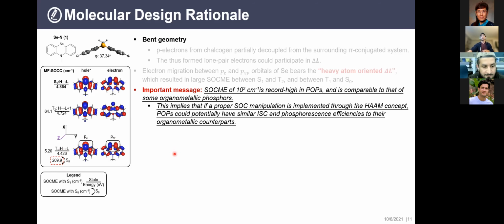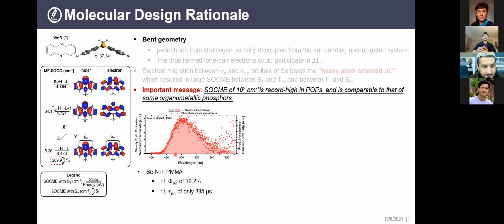And more importantly, when you get a spin-orbit coupling value of more than 100, you are expecting a very fast lifetime in the microsecond region, not in the millisecond region. So we actually made this material and doped it in polymer to visualize its performance. And we found that while it emits very bright phosphorescence with a quantum yield of 19% at room temperature, its lifetime is only 385 microseconds, which is actually very fast among purely organic materials.